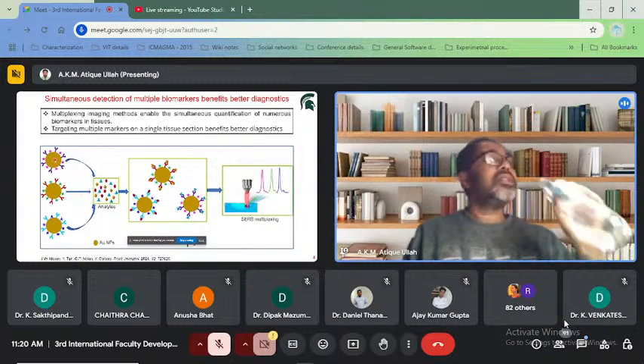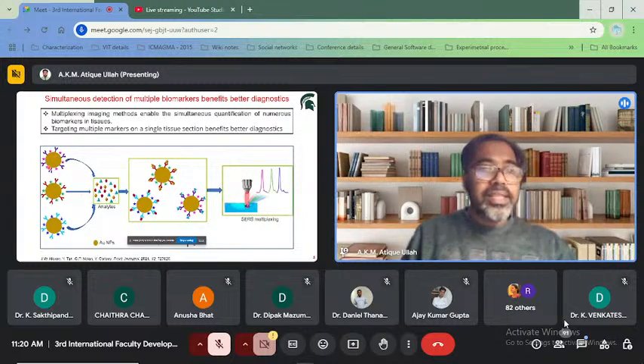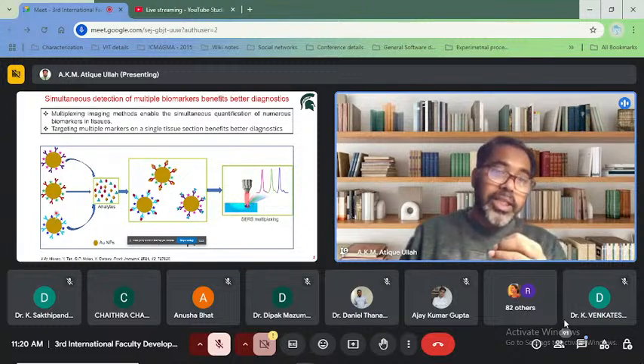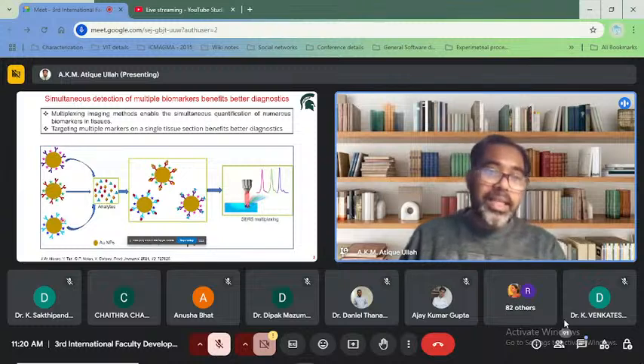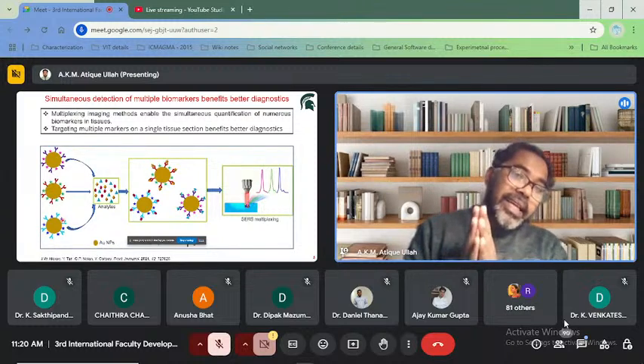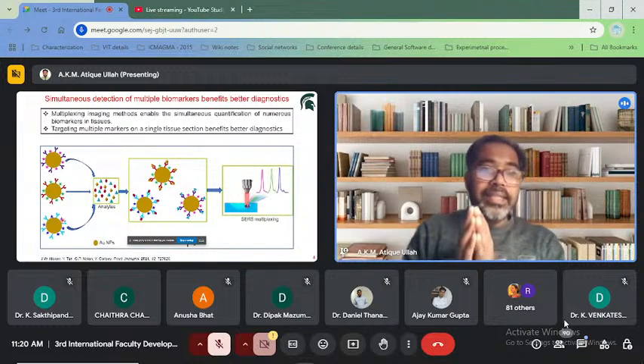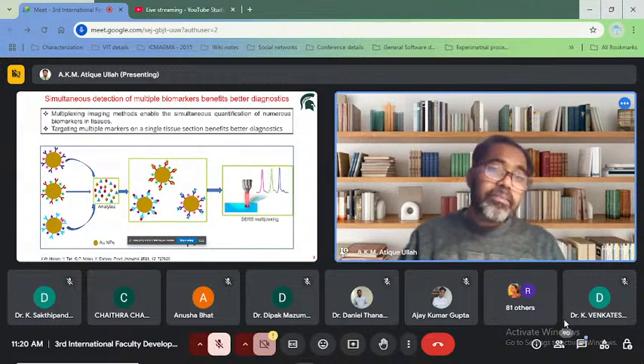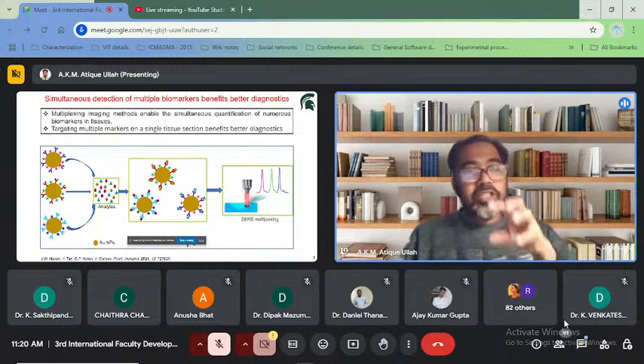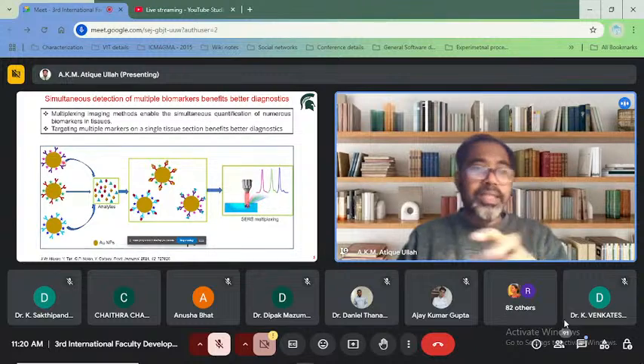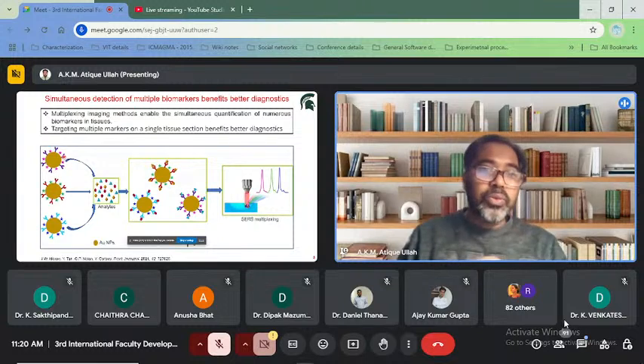Suppose this is a gold nanoparticle. You can see the gold nanoparticles. Suppose the gold nanoparticle is functionalized with 3 different reporter molecules, which I have shown here. Each Raman active molecule has its unique spectral signature. When the gold nanoparticle is functionalized with the Raman active molecule, it is called a SERS nanoparticle. And the SERS nanoparticle is functionalized with different types of ligands. You can see these are the ligands.